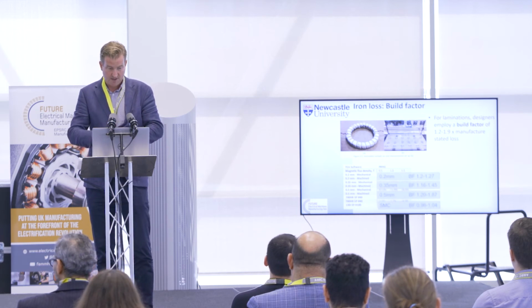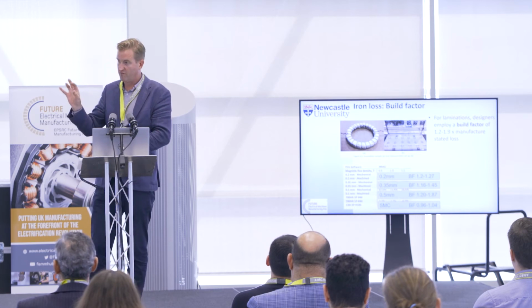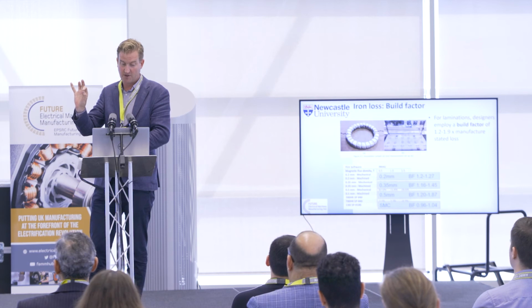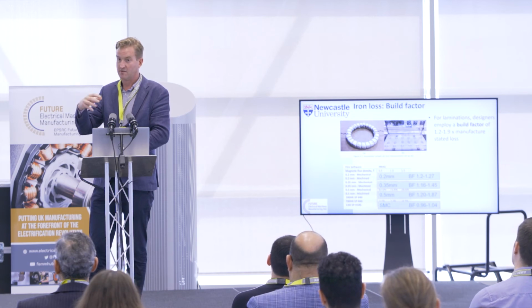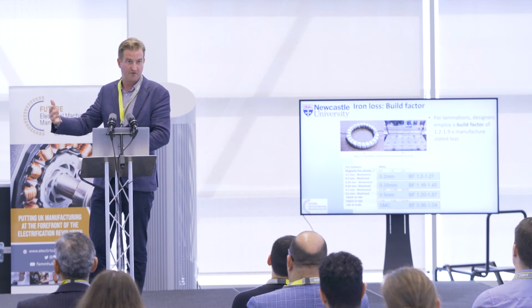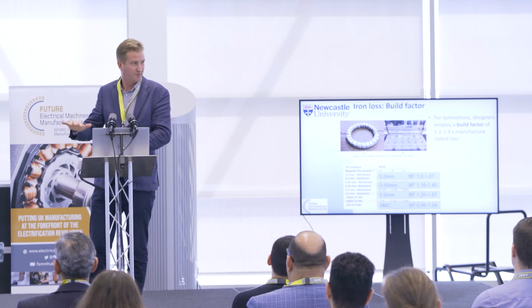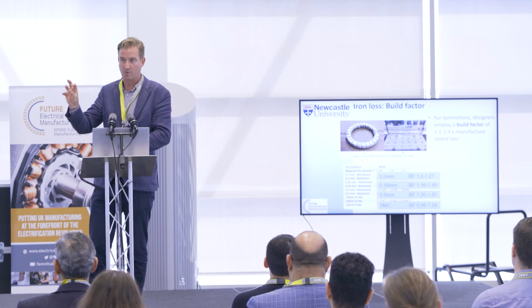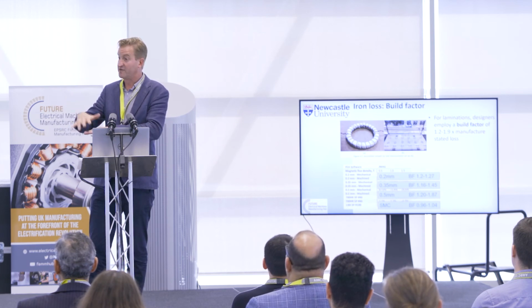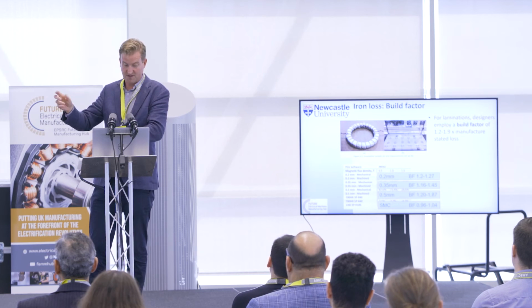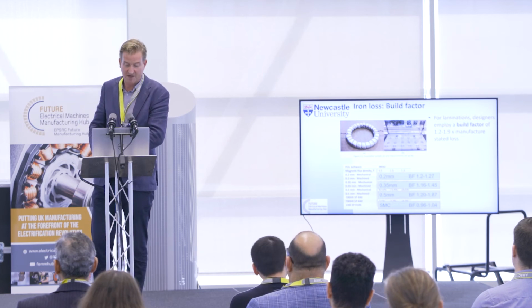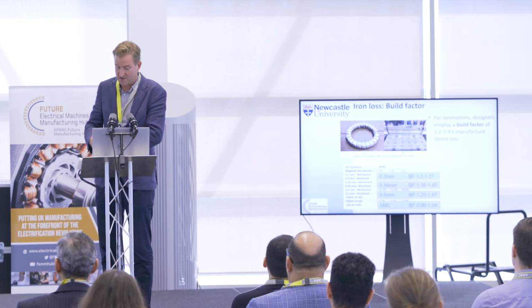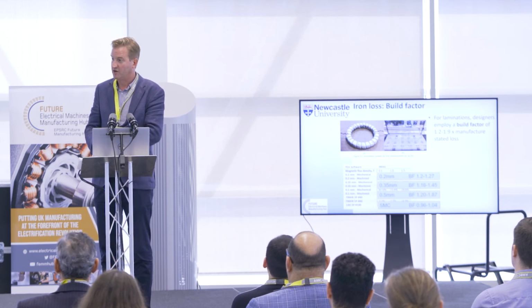And you'll notice for the thinner laminations, the difference between what the manufacturers tell us the iron loss is and what we're actually measuring is something like 27%. So we're measuring more iron loss than we're expecting. For the thicker laminations, that gets worse. We're at up to 45%, or for the 0.5 lamination, we're almost heading towards double the measured loss compared